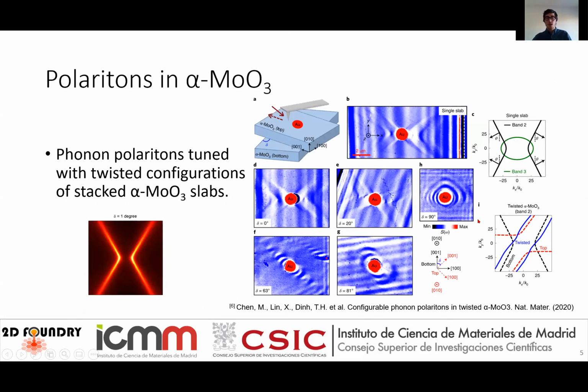But also, a month ago this paper was published by Chen and Jarillo and their companions, in which they place slabs of molybdenum trioxide one on top of another at different angles, and they say with the same technique, this polariton dispersion, these are real images, and they see this polariton dispersion, and they change the angle of the two slabs, and you can see the difference of dispersions as you change the angle of the two slabs from 0 to 90 degrees. And also they made this calculation.